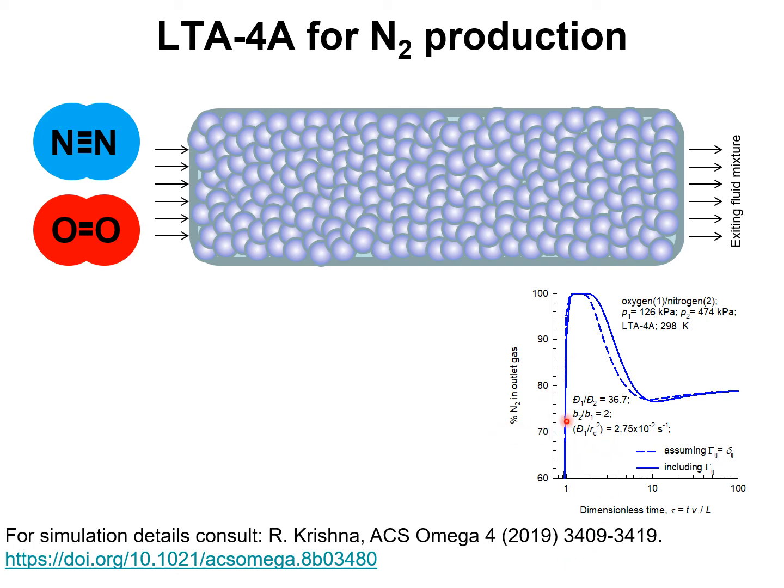Since the objective is to produce purified nitrogen for a desired purity, say in excess of 90%, we note that the model in which thermodynamic coupling effects are duly accounted for yields a higher productivity of purified nitrogen. And this is in agreement with the analogous result for separation of nitrogen-methane mixtures using LTA4A zeolite. Inclusion of thermodynamic coupling improves the separation performance of nitrogen-oxygen mixtures.